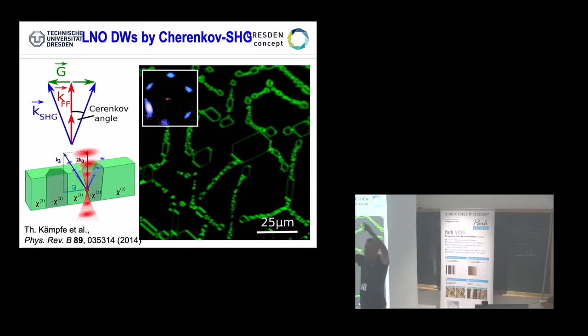And that's now the point. By this kind of hemispherical incident light, we find at any point when hitting the domain wall a phase matching condition per se for free. We don't have to do too much. We don't have to rotate, simply because the domain wall is so forgiving, giving us the phase matching for free. And that's really the nice thing. And then the second harmonic, Cherenkov light, comes out at a larger angle. It's not the same angle as your direct light; the Cherenkov angle is much larger. You see that here.